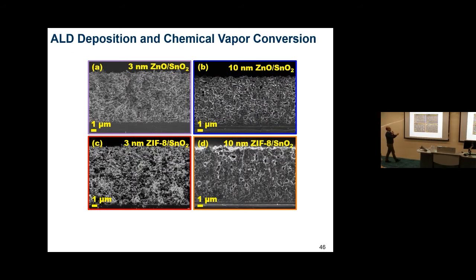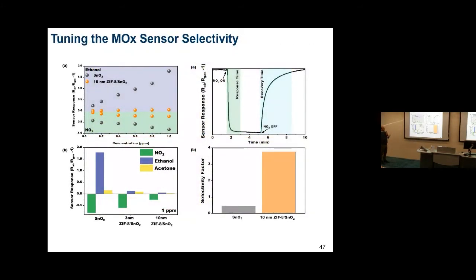Here you can see what happens when the zinc oxide is 3 nanometers and 10 nanometers in the porous network, distributed everywhere, and what happens when you convert it to a MOF, to ZIF-8. You start filling the structure, and when you do that, you basically start changing the response quite dramatically.